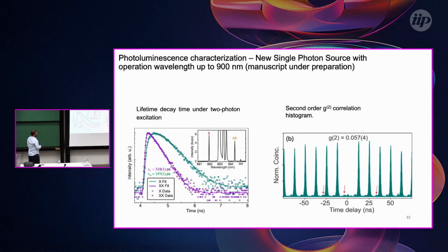Also, another advantage is that, in general, as you know, the lifetime of these indium arsenide quantum dots is on the order of 1 nanosecond, but for the droplet etching method, this is almost a third of the time. And this is really nice because you can operate in gigahertz. If you put this kind of quantum dot in a cavity, you can make a device that can operate in gigahertz. And also with this lower lifetime, we improve the photon indistinguishability.